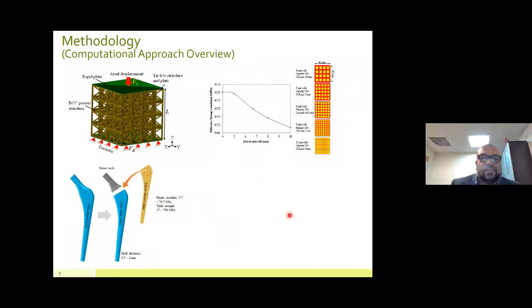And once we had designed the porous structure, we embedded it into the stem, where the outer part is a dense shell and the inner part is the porous structure. So this whole combination gives us our femoral stem. Again, to repeat, the outer part is a dense shell within 0.5 to 2 millimeters. These are our design parameters. And inside of this dense shell is where we embed the porous structure made from titanium.